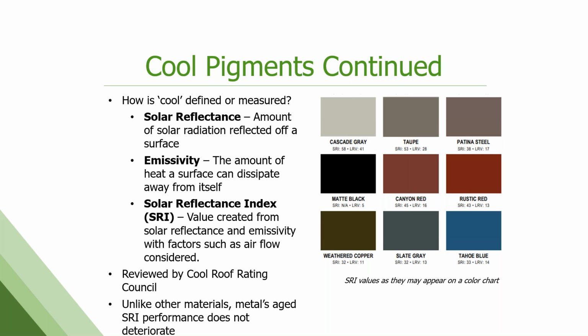One interesting thing about pre-painted metal that is a huge advantage is that its SRI value does not deteriorate over time like other roofing substrates do. So, you know, typically it's an initial rating and a 3-year aged rating. And you will see if you go online to the Cool Roof Rating Council that pre-painted metal 3 years out from its initial has the exact same SRI value it did initially. And you can go 10, 20 years out and that SRI value does not deteriorate on pre-painted metal. And it's because these coatings have such great durability. They're not degrading, they're not fading, they're not changing over time, which we think is a huge advantage for this product.